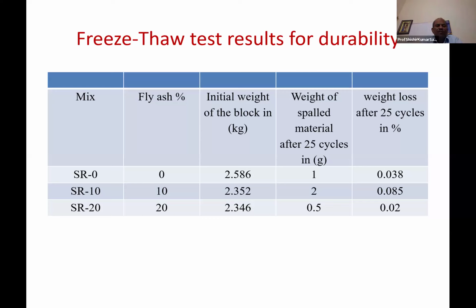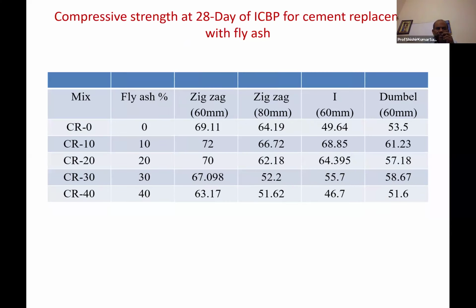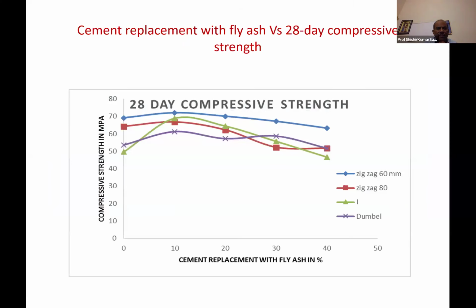Freeze thaw test for durability. Initial weight, final weight, and you can see the percentage, and it is less than 1%. 28 days of ICBP with cement replacement with fly ash. So here you can see with addition of fly ash, this increases, then starts decreasing, but it is more than the original one. So based on this, the corresponding shape has to be used after proper testing.